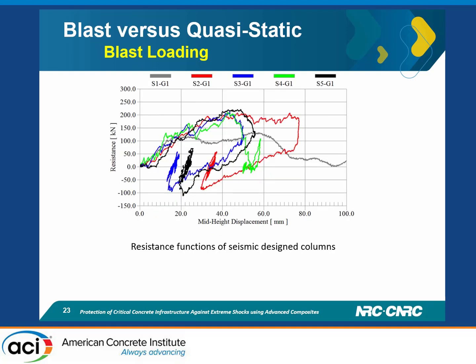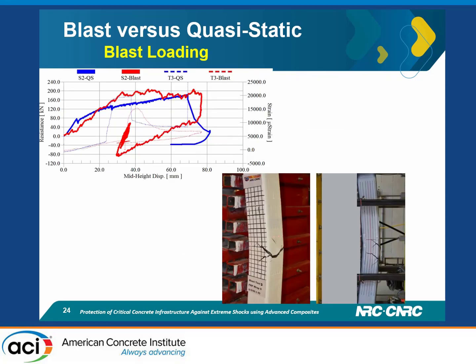And here with the seismic, we have better performance, of course, and the FRP is also modified for seismic versus non-seismic to fit the behavior of the column and what is predicted to be the best behavior. As you can see, the energy is increased, which is the area inside the overall cycle of the loading. Here is an example of the damage when we are using plus minus 45 FRP. As you can see, the damage is really changed, and I will show you some videos of the tests, which show how the damage changes with the FRP orientation.